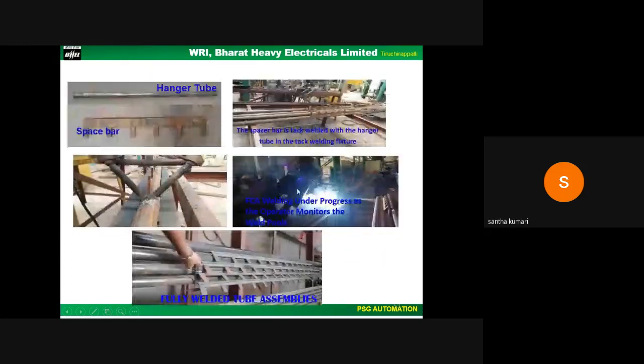Here, another recent development is hanger tubes. These are called hanger tubes. This has to be welded with a plate with similar arrangements. The hanger tubes, as you see in the photographs, are fabricated by placing the strip on the plate wherever we call has to be welded on tube, which had been carried out by the SMAW process earlier by employing two SMAW welders for every hanger tube welding to avoid distortion.